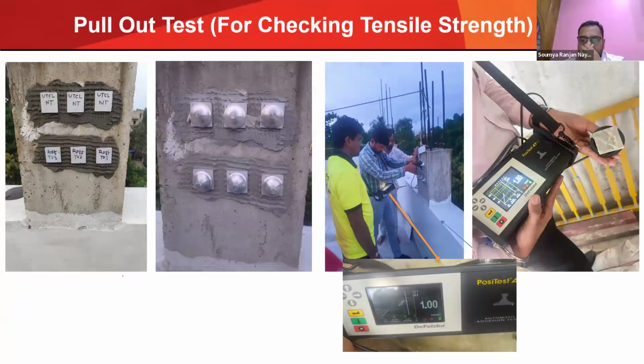Yeah, this is the test I was saying. These are 50 mm by 50 mm small tiles. This is the pull-out test for tensile adhesion strength of the tiles. As you saw, type 1 should show 1, type 2 should show 1, type 3 should show 1.5. These are the ways we check the tensile adhesion strength.